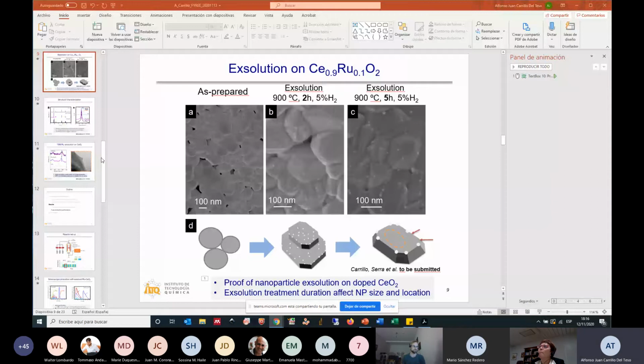Certainly, that's an interesting question that we should look at, but probably, in the exsolution field, it's well known that if you increase the temperature or time of the solution treatment, you will have larger particles. So maybe these particles prefer to go to places in which surface energy is lower, such as grain boundaries or edges. But I don't have an accurate answer to this question since we haven't looked at it yet.